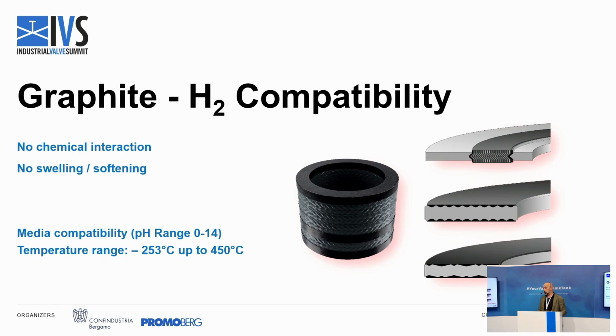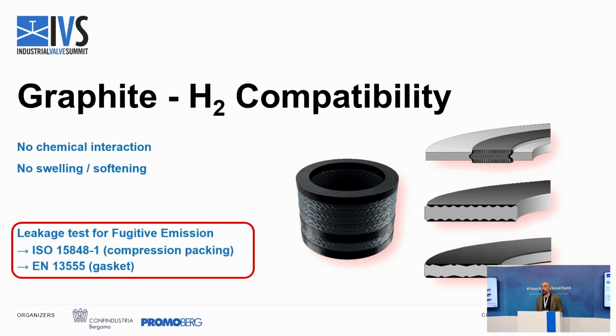Of course, after that, we also have the graphite, the compression packings. Again, there's no chemical interaction. There's no swelling or softening whatsoever with hydrogen. The media compatibility of graphite is basically infinite. There are very few chemicals that can interact chemically with graphite. The temperature range is also very interesting for the hydrogen industry because it can also work with liquid hydrogen. So again, how can we be sure that the graphite rings or the graphite gaskets can work with a low level of leakage? I'm talking about fugitive emissions performance.